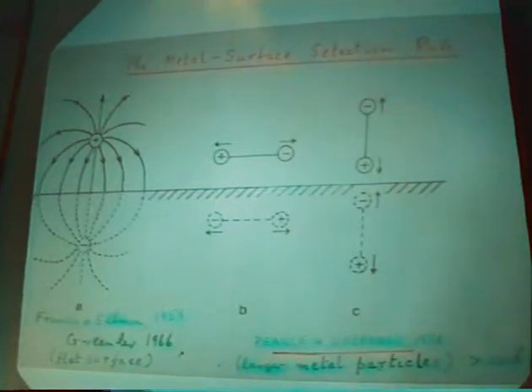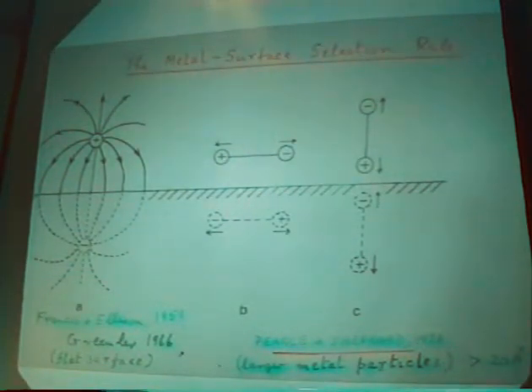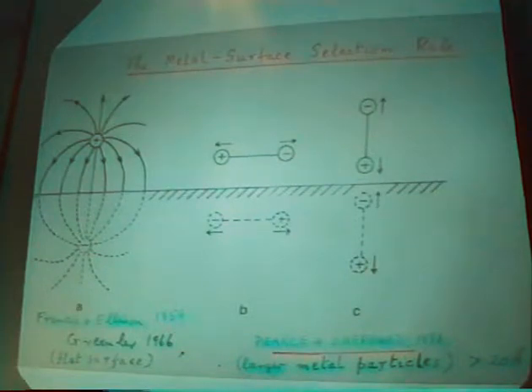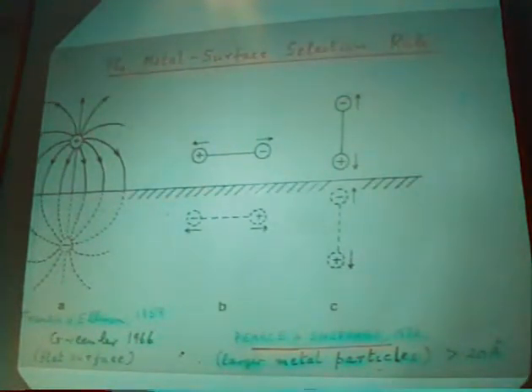Now, supposing you have a vibrating dipole moment giving infrared intensity parallel to the surface, it should have an image, effectively, with the opposite sign. So if you were looking for, say, radiation from this, there would be radiation of the opposite phase, which would cancel out, provided the image was perfect. But in the infrared, of course, metals are very good conductors. On the other hand, if you put the dipole perpendicular to the surface, the image actually reinforces, and you can expect to get a stronger band, provided your infrared radiation had an electric vector roughly perpendicular to the surface. And therefore, as Bob Greenler earlier pointed out, what you needed to do was to reflect the light off at near grazing incidence. But supposing that was true for our larger metal particles, then this would have influences on the spectrum that we would see.